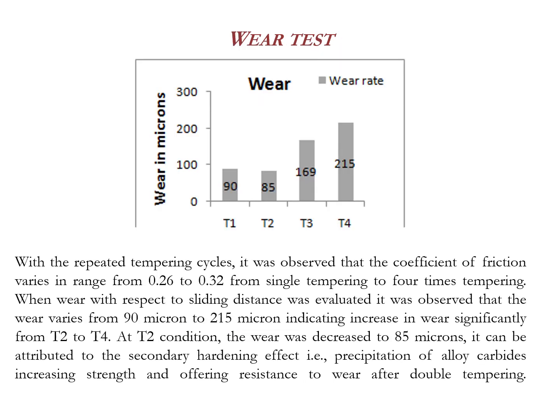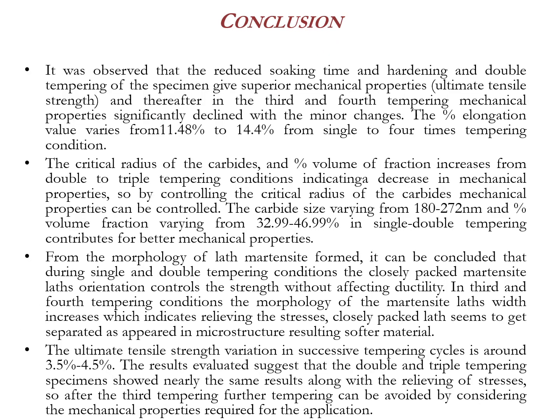Wear test. With the repeated tempering cycles, the wear rate varies from 90 to 215 micron, and at double tempering condition, the wear was minimum, which can be attributed to secondary hardening effect, that is precipitation of alloy carbides, increasing strength and offering resistance to wear after double tempering condition.